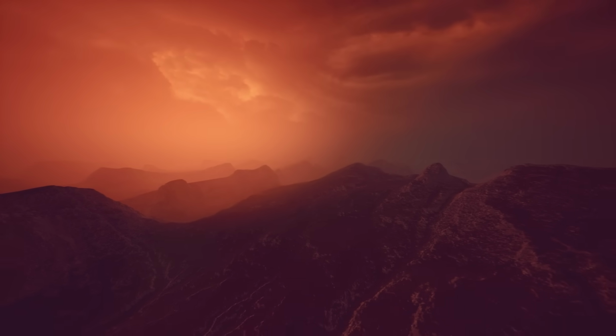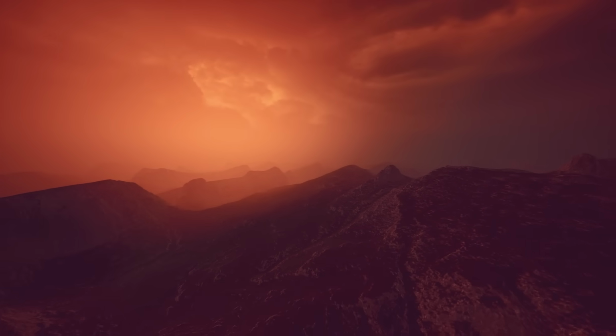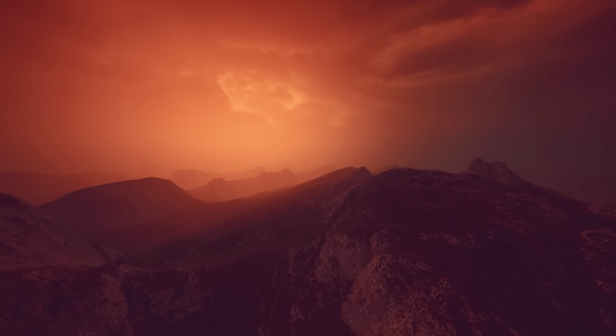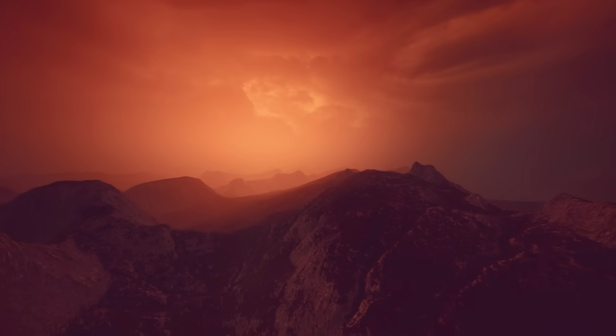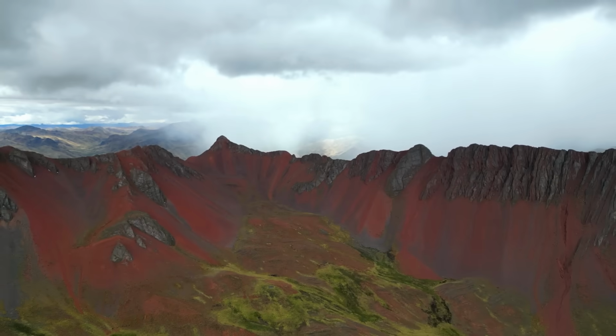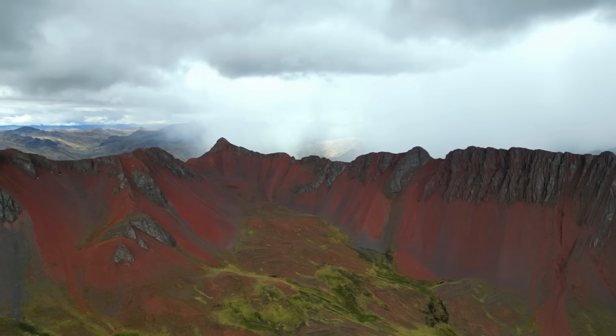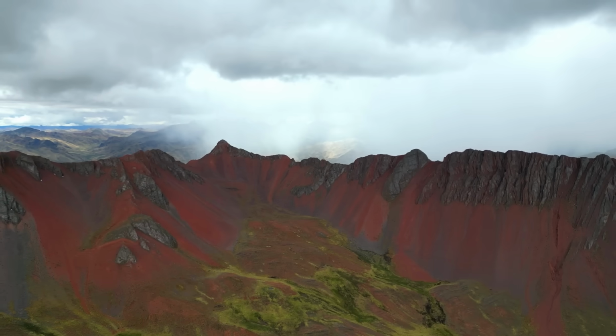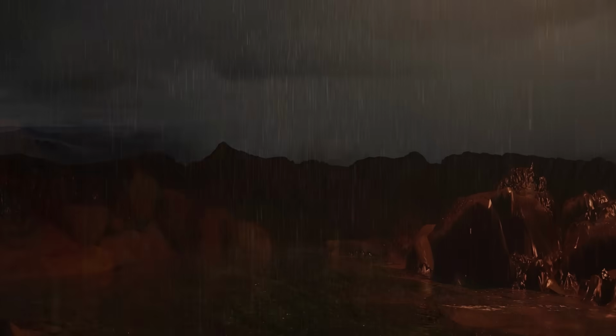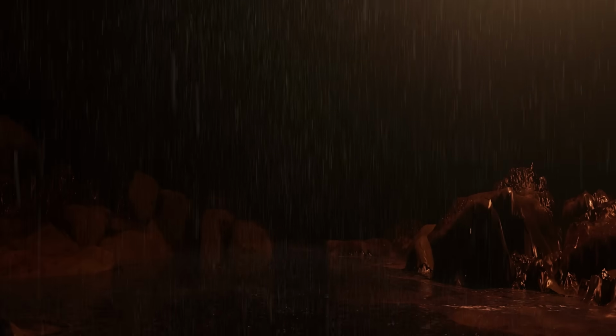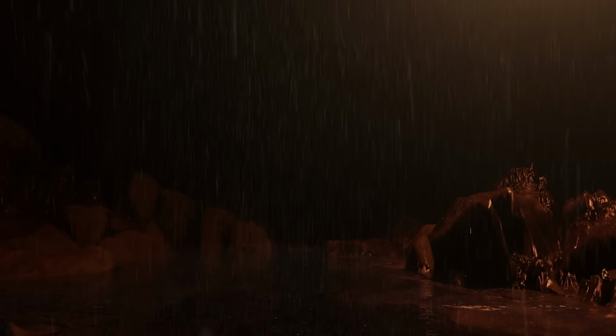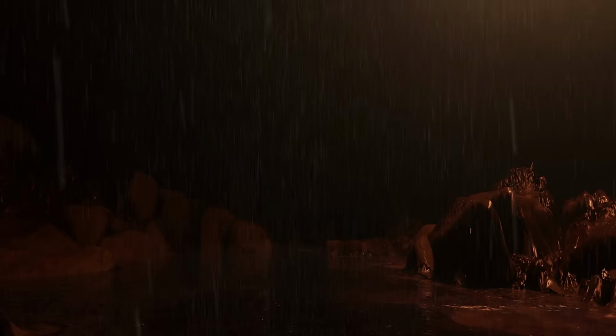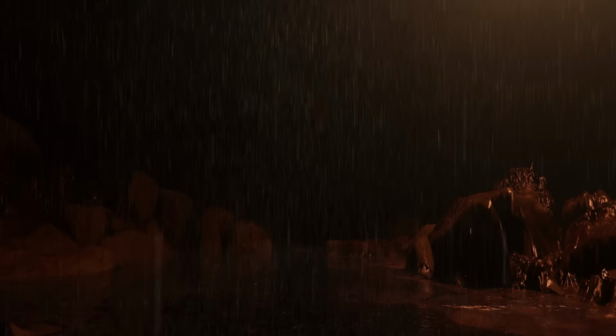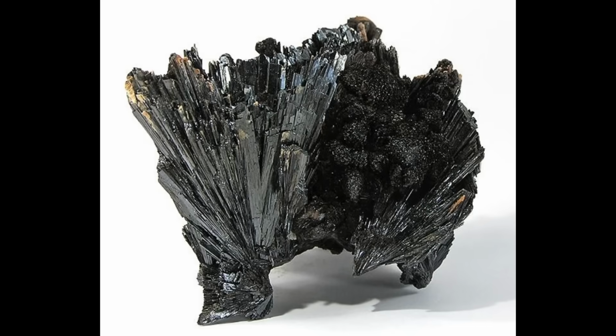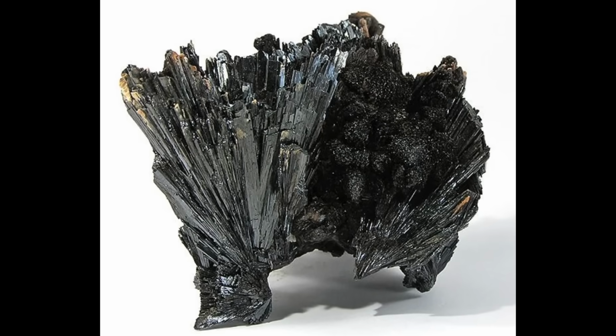Then time takes over. As those sulfide-rich rocks are uplifted closer to the surface, they enter a completely different environment. Oxygen becomes abundant, water starts circulating, and that's when the chemistry begins to change everything. Sulfides are not stable in these conditions. They begin to oxidize. The sulfur component reacts with oxygen and water to form sulfuric acid, which further accelerates the breakdown of the surrounding minerals. The crystal structure collapses. Iron is released and rapidly oxidizes into iron oxides like hematite, limonite, and goethite, those deep reds, yellows, and browns that stain the rock.